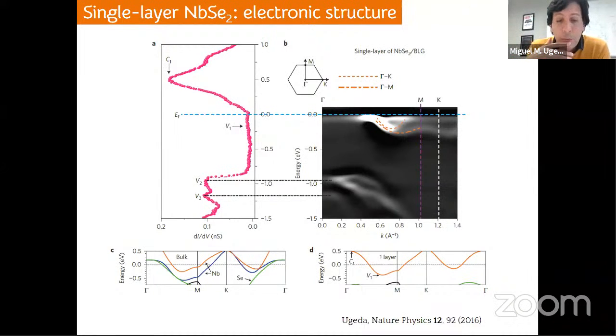In terms of the electronic structure for niobium diselenide, we demonstrated, or some of us demonstrated, a few years ago that the electronic structure becomes quite simple in the monolayer limit. Here I show you a large-scale ARPES spectrum where you can see the dispersion of the two pockets in these materials, particularly this pocket here and this pocket here. The fact that you see them in the same spectrum is because there is some sort of rotational disorder in the niobium diselenide sample with respect to graphene, and that makes us lose the angular resolution. But other than that, we can still distinguish these two pockets.